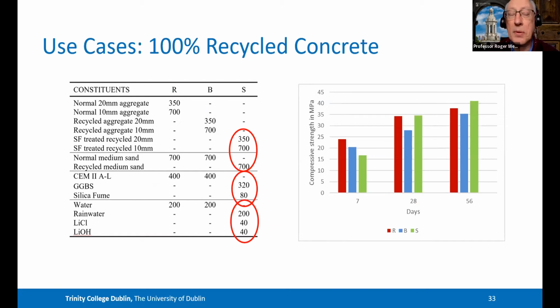And we've used 100% non-Portland cement, and we've used lithium, not usually used, but we got hold of some recycled lithium, and it took us a year or two, but we demonstrated very clearly that lithium is an effective alkali activator, which meant that we didn't need to use anything other than a recycled material to activate the cements. And we use solely rainwater. So we had a procedure for gathering, testing, and using filters to use rainwater in concrete. And as you can see from the graph on the right, at 28 days, the green one, which is what I would call sustainable concrete, achieved the same strength as the parent material after 28 days. So 100% recycled concrete has been demonstrated to be usable.